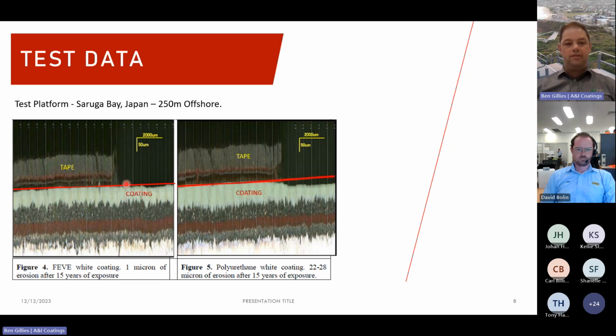These particular panels were placed on an offshore structure off the coast of Japan. What we have on the left side here is fluoropolymer, and on the right side is polyurethane. After 15 years, you can see the polyurethane has lost 22 to 28 microns of film thickness. The fluoropolymer has lost an average of 1 micron. So the fluoropolymer essentially is still doing its job of protecting the underlying coats, which in turn protect the substrate. When you actually look at this on a structure, what you'll see is a tired looking coating. It'll be chalky, potentially started to crow's feet. And what it really does is it starts to create a pathway or a weak spot for corrosion initiators to start to get to the substrate.